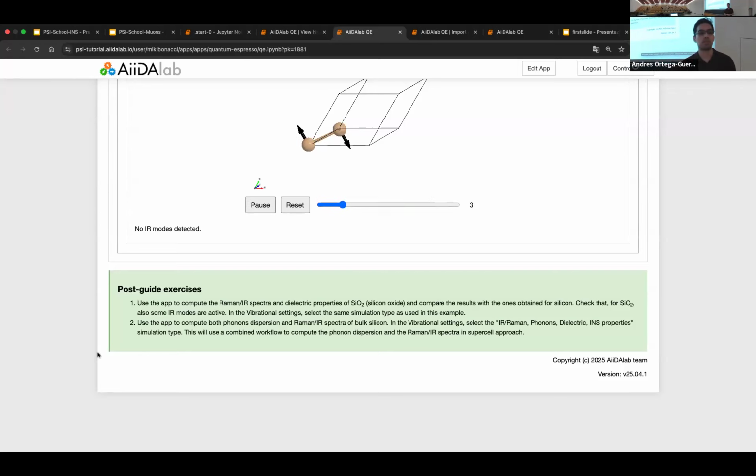For example, at times a system doesn't display a band gap if you are working as a closed shell, no magnetization. But maybe once you put magnetization as antiferromagnetic, you will actually open the gap a little bit. So remember these details, otherwise you will not get a system with a band gap and will not replicate.